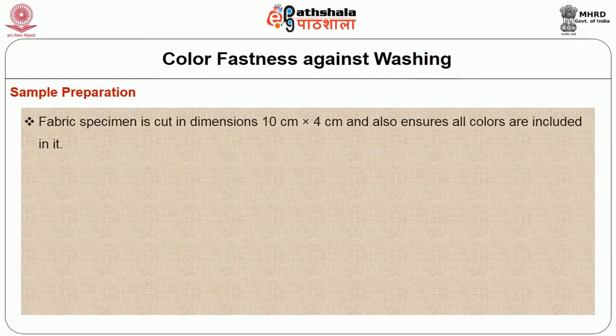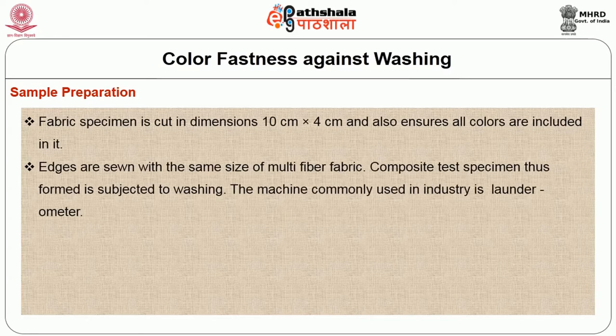Sample preparation. The fabric specimen is cut to dimensions of 10 cm by 4 cm, ensuring all colors are included in it. Different dye shades are included. Edges are sewn along with the same size of multi-fiber fabric, any woven fabric. The composite test specimen thus formed is subjected to washing. The machine usually used in industry is the launderometer.